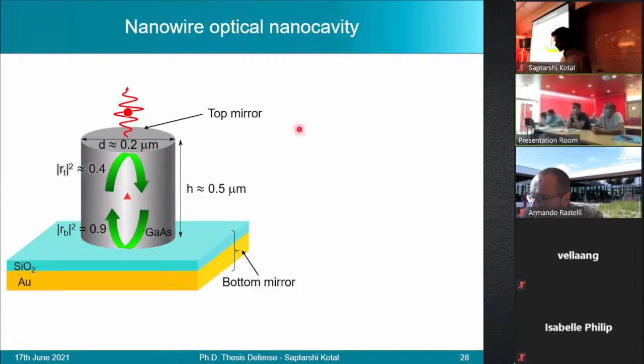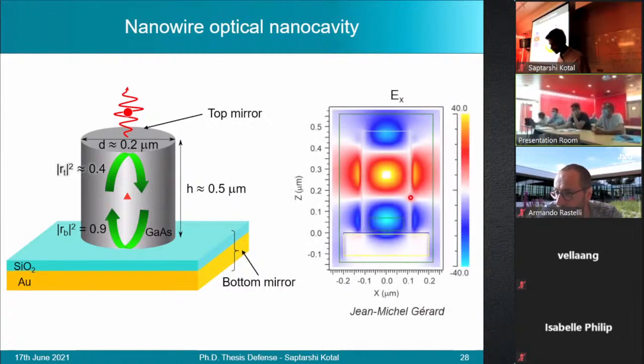Next, we choose a diameter of around 0.2 micrometer, which has been shown to be a good diameter to work with in our previous samples, to obtain a good transverse confinement of the mode and a strong inhibition into the free space modes. And we decide to work with a cavity of the order 3, which results in a height of the cavity of the order of around 0.5 micrometers. The quantum dot is then positioned on the first antinode of the cavity mode.